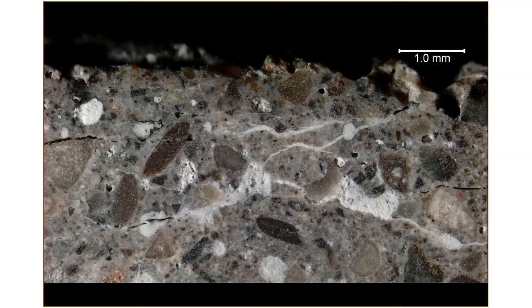There's been a lot of talk lately. A lot of concrete technologists are talking about self-healing concrete. Well, here's a 125-year-old pavement that is your first occurrence of self-healing concrete. It's been happening for 125 years. So we got some scaling, some incipient scaling or incipient spalling in this concrete that stayed in place long enough for the concrete to self-heal and fill these cracks with secondary calcium carbonate. The latest technology, the latest people talking about this, is about producing concrete with a bacteria that produces calcium carbonate as a secondary deposit and self-heal cracks. This is what's been going on here in this pavement.